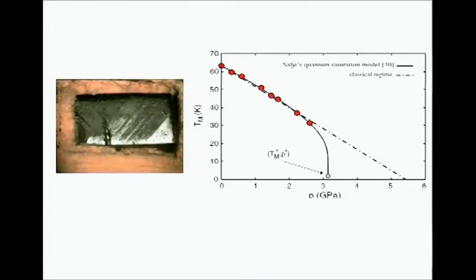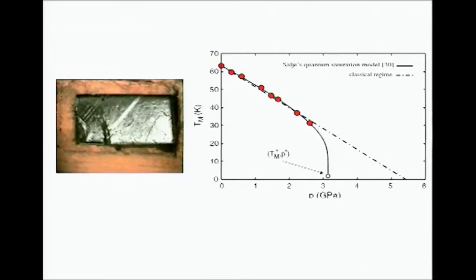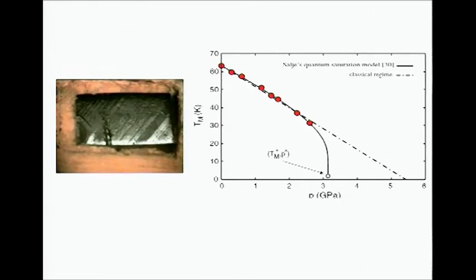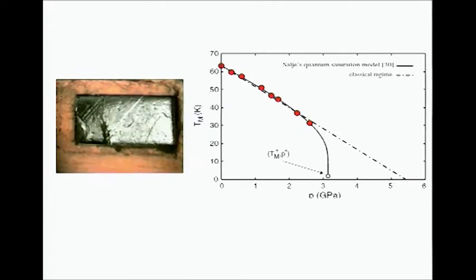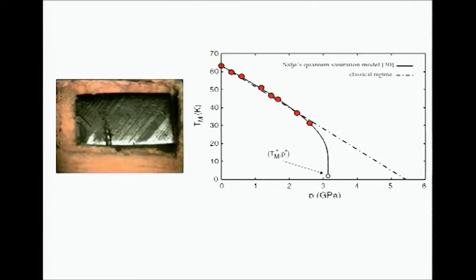I also looked at the pressure dependence of some of these, and you can see that with modest pressure you can squeeze out the martensite phase. So this is the martensite phase, this is the parent phase.